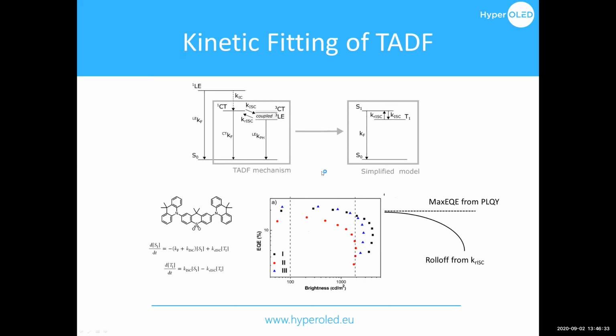And the reason that these numbers obviously are important is that if you then go on to make an LED out of a particular TADF material, the maximum EQE that you can hope to get is really determined mostly by the PLQY, which is relatively straightforward to measure.